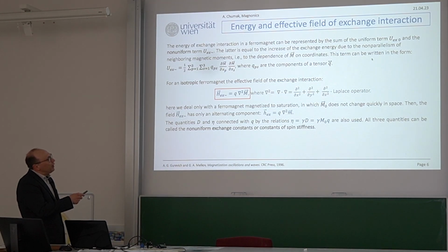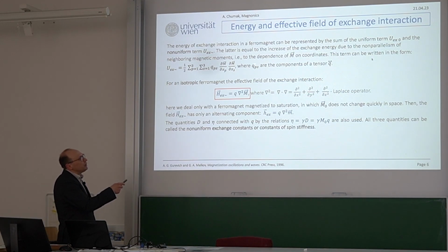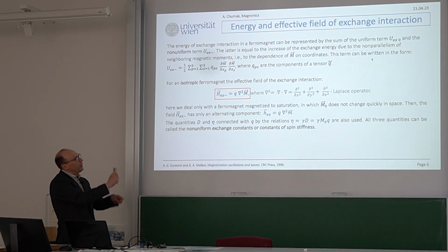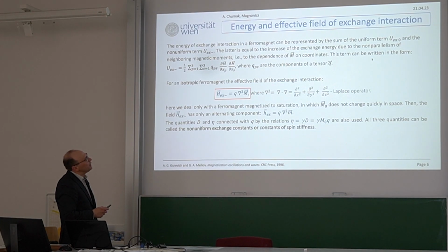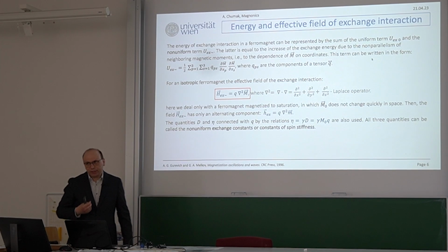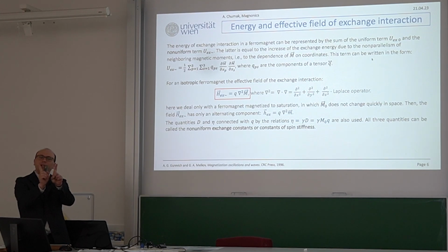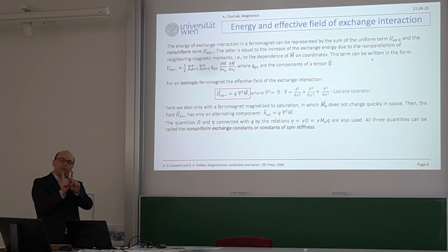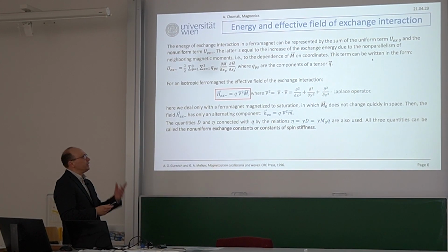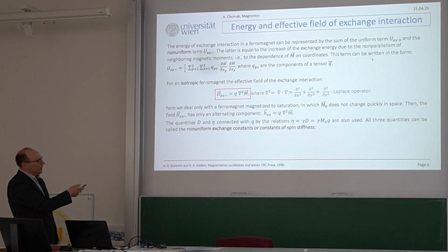And what we do afterwards, we just simplify our formula for an isotropic ferromagnet. So isotropic means that this one is constant, it's the same, doesn't matter in which direction we go. And what else we do, we principally neglect the static case because we are interested in exchange energy coming particularly from dynamics, from the precession of spin. So when the angle between two neighbors is not zero anymore, that increases energy, and that's what is of interest for us. Therefore, we can rewrite this